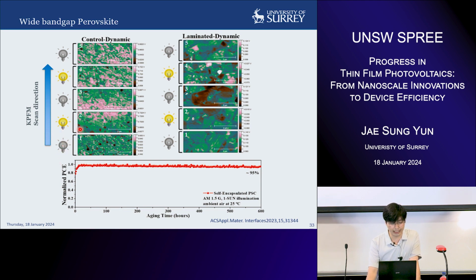And you can see when the light is on, there's some regions with different work functions starting to happen. And even when we turn off the light, those regions remain the same. So there is going to be a very non-uniform distribution of the work function and charge generation, whereas your laminated sample, so one that got bonded, has a very stable and uniform work function and charge generation.